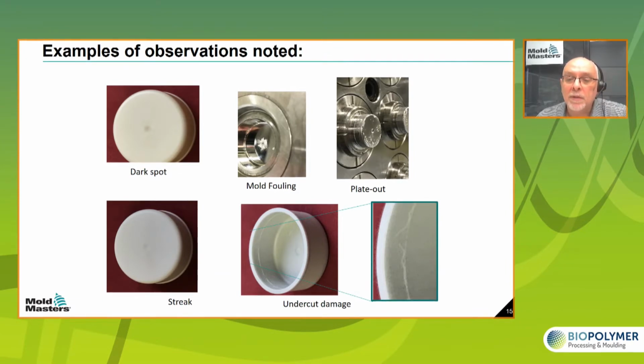Also plate out. So here we can see there's a buildup happening on the cores with a certain material that may cause some clogging of vents, for example, which may result in a different defect appearing on the part. So it's good to know that these are concerns with each of these specific materials. We see a very slight streak occurring that may or may not be objectionable. If it's a medical application on a white part, then it is probably not going to be acceptable. And we may need to use a different gate style or make some modifications to accomplish a better gate performance for that material in those types of applications.